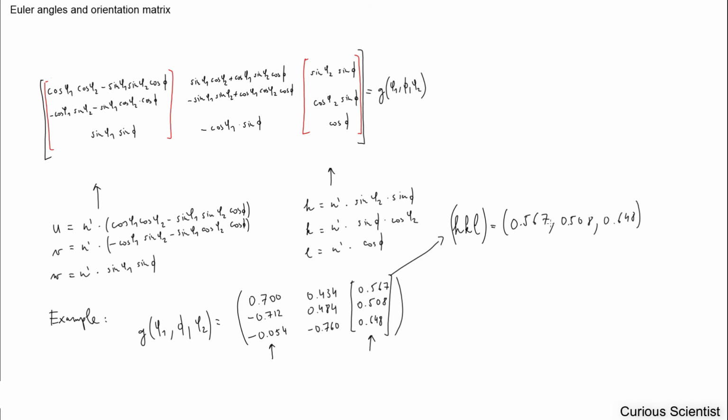Here what you try to do is find the closest integer of this. What I would do, I would pick the largest number. In this case it is 0.648, and then divide all of these by 0.648. So you divide everything, and then you will see that it will look like this.